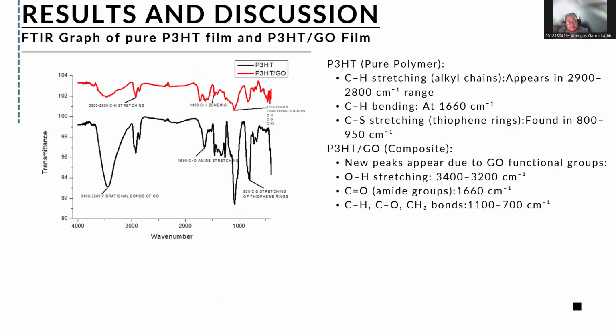So on the black line, we will see the pure P3HT will have a carbon to hydrogen stretching, which is the alkyl chains, that will appear in the 2900 to 2800 range. Then it will bend at the 1660 range. Then a carbon to sulfur stretching, which is the thiophene rings, will be found in the 800 to 950 range.